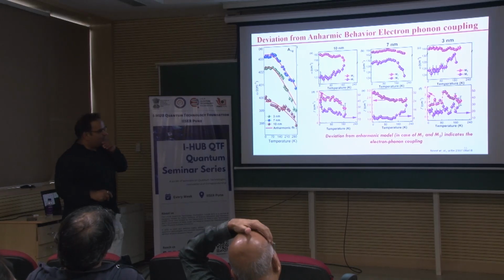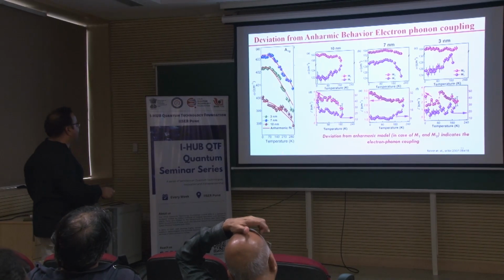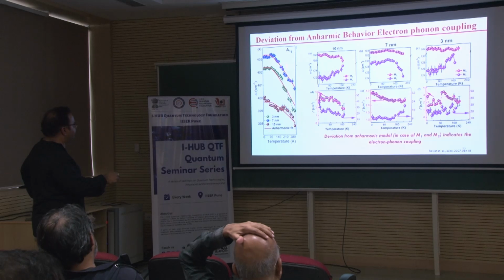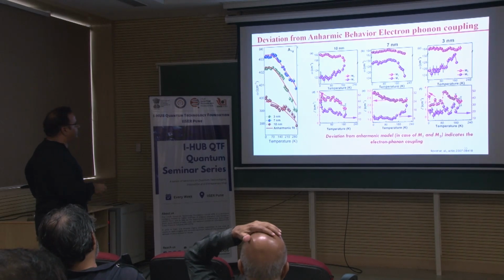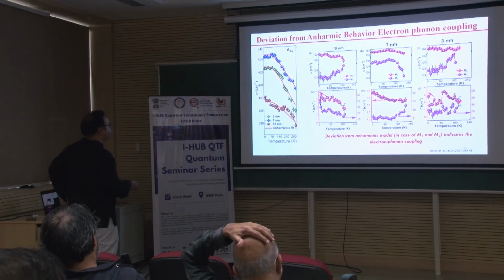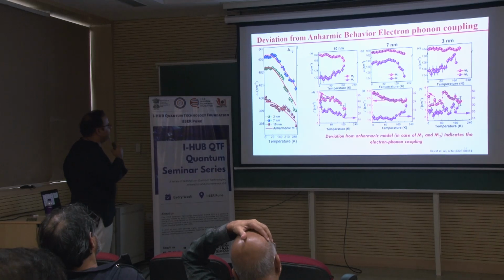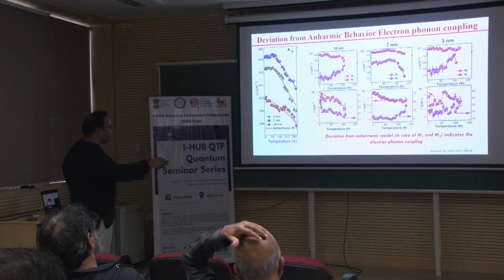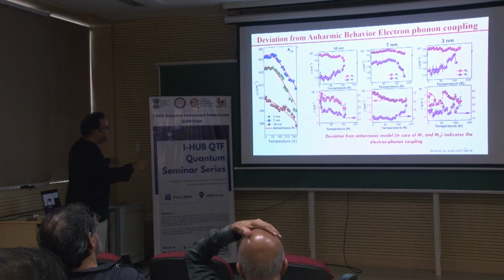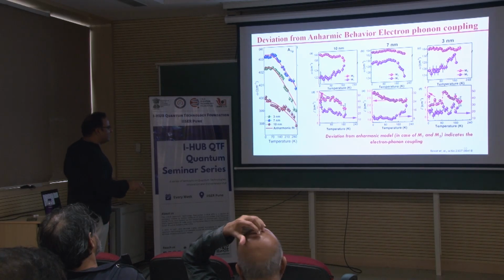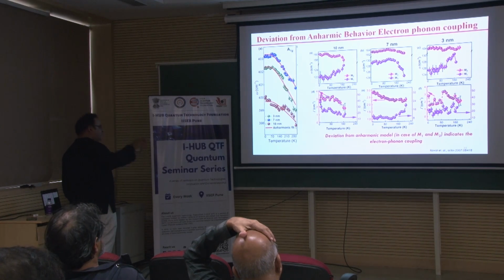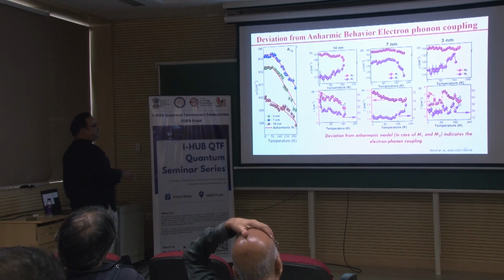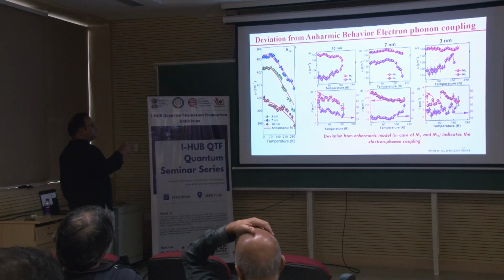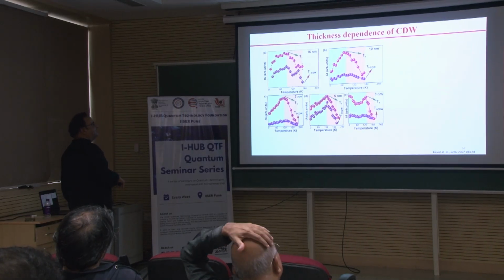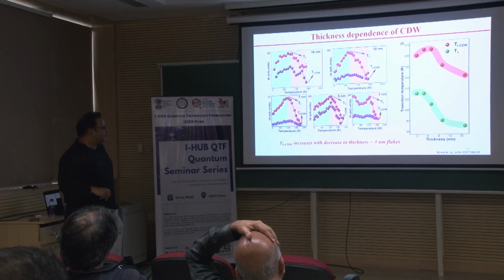Then we also identified from the deviation from the anharmonic behavior that if the deviation is there, then you have more involvement of the electron phonon coupling in these materials. I will not go into the details of all those here, because they all are giving the same message that you have a large electron phonon coupling which is specific to the tantalum sulphide, and that is what, as I mentioned, we chose because we wanted to see how much the electron phonon coupling is. So, let me conclude it here.